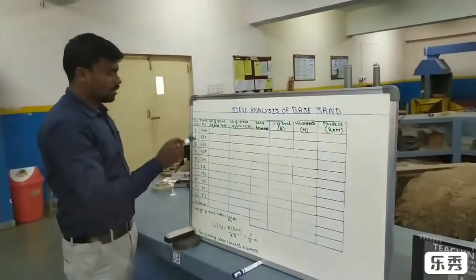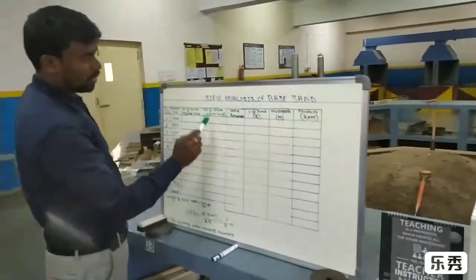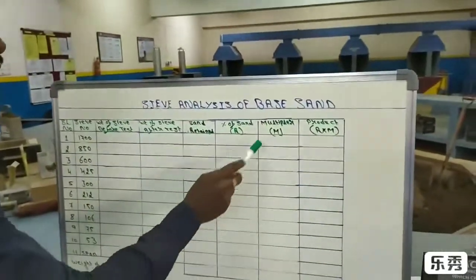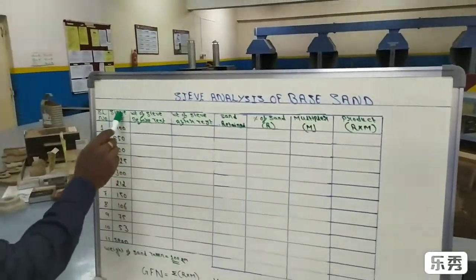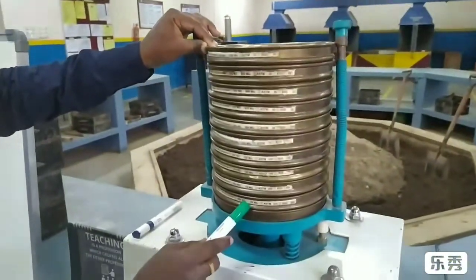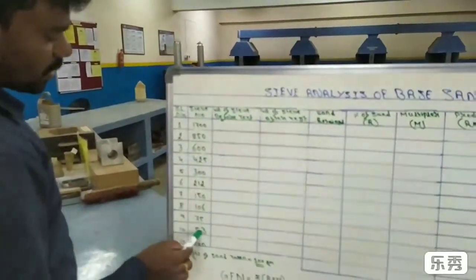When doing the sand testing, first we write the tabular column for sieve analysis. Here we write: serial number, sieve number, weight of the sieve before test, weight of the sieve after test, sand retained, percentage of sand, and multiplier product. We note down the sieve numbers from 1700 to 53 microns — totally 10 sieves, plus one pan.